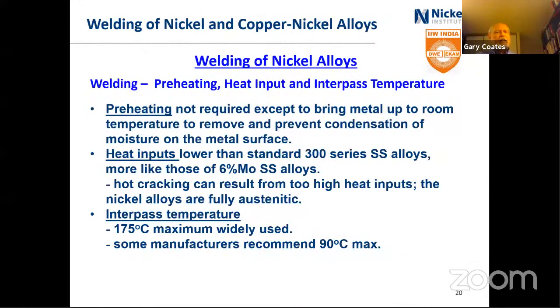So we mentioned that preheating is not normally required, but in environments where there's high humidity and you want to remove any moisture contamination, sometimes people will take an oxyacetylene torch and just warm up the material so that it's warmer than the ambient air temperature, and you have no condensation on the material.